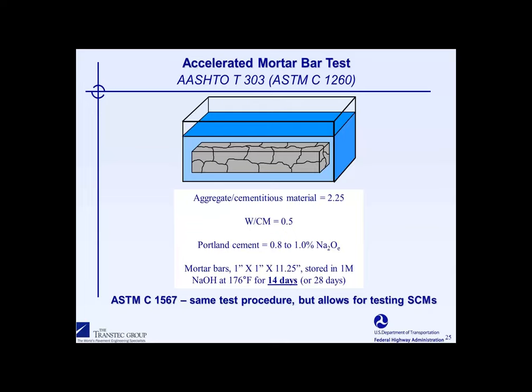So this is a very aggressive, high temperature test, and it's essentially an infinite supply of alkalis that is provided to the specimen during the course of the test. The idea is for the external alkali solution to penetrate into this bar and to cause the aggregate to expand, and the expansion would then be monitored.